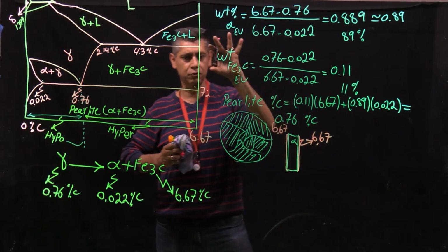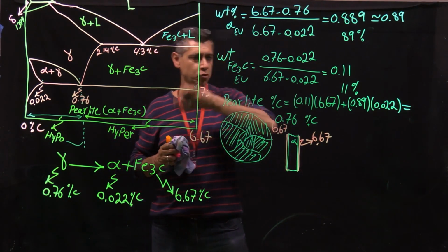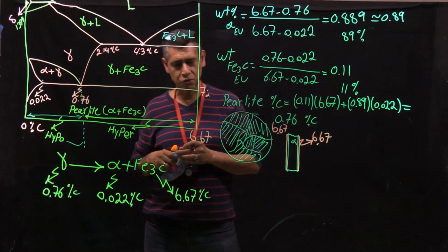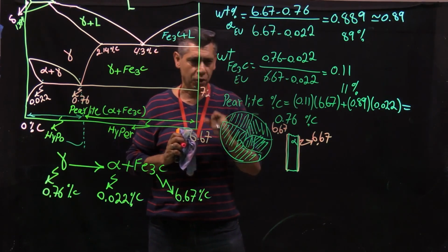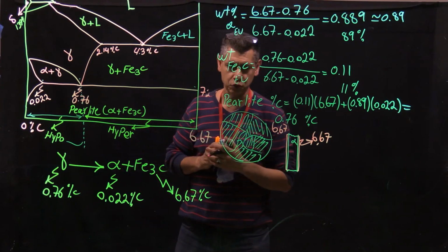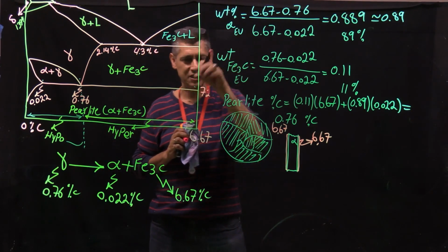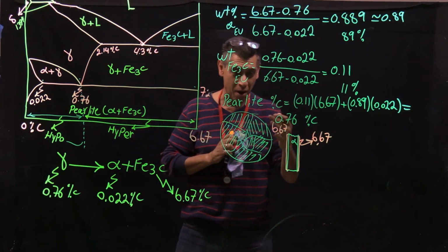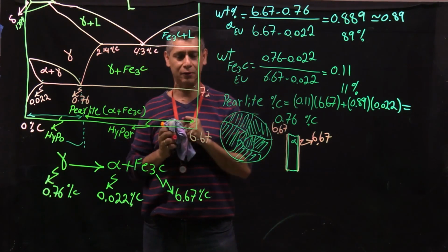When you look at the microstructure under the optical microscope, I mentioned many times, you see dark and white. Students often say the dark one is carbon. That's not true. This is an optical microscope. First of all, if you polish the surface and look at the microscope, you will see nothing, just some superficial scratches. You have to etch the sample. Etching means you introduce a mild acid, and that mild acid brings up the grain boundary.